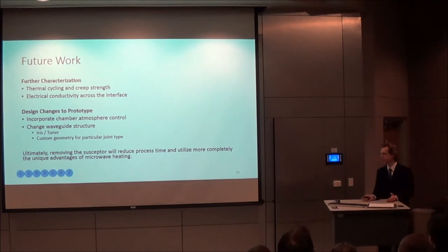In addition, by using the susceptor, I'm actually heating the base materials just as much as I'm heating the interlayer. And lead telluride and copper don't have very different coefficients of thermal expansion, so it's not as much of a problem with this particular application. But if you're using something like alumina to aluminum, for instance, that difference is a lot more significant, and it could prove problematic. So if the heat could be generated right at the interlayer, and the whole base materials don't themselves heat up, then not only is it going to take less energy and take less time, you're not going to have those problems that could be introduced by the different properties of the base materials. So it's more ideal. I could also think of it as more scientifically pure to heat just the interlayer itself.